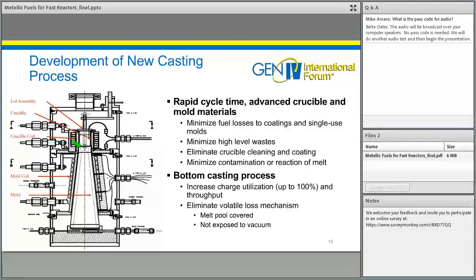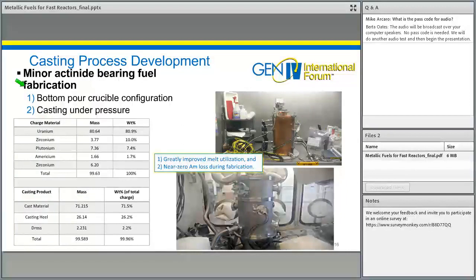But also, since you're draining the crucible from the bottom into the mold pallet below, it allows you, in theory, to utilize 100% of the charge of every casting batch. And so these things have greatly improved casting and minimized the waste associated with the traditional approach. So we've done a lot of testing along these lines to make sure that they do in fact bear out in practice and not just in theory.